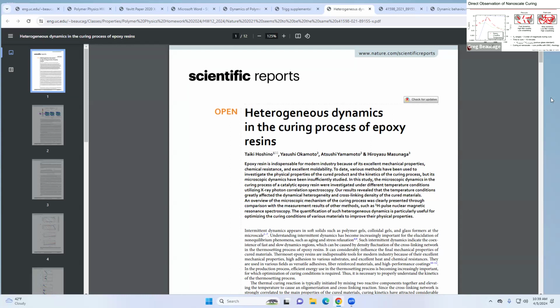And then that was kind of our hypothesis in the beginning. I should have shown that first, sorry. But our hypothesis was, again, in the pre-cure state, these guys would be moving around real fast. You'd have high mobility, low cross-linking. And then once that epoxy cured to form a nice adhesive, those things get stuck in the matrix and they don't move around a lot, right? Yeah, so that was really exciting. We like this because it's a commercial material, right? We just took this off the shelf, we threw it into the beamline, and we got nice quantitative data. And you could use that information going forward if you want to process it differently, try different cure reactions, different cure chemistries, whatever.